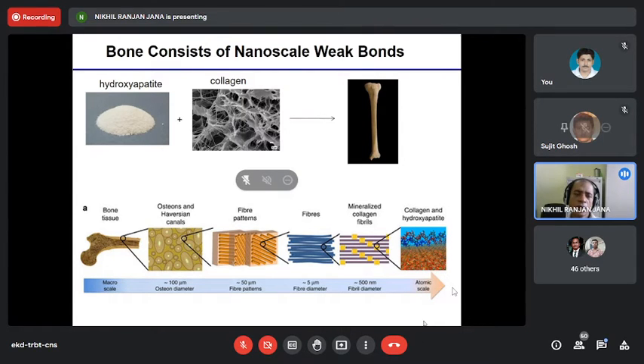Interaction between inorganic nanoparticles, hydroxyapatite nanoplatelets, with collagen fibrils, fibrillar organic materials, via multiple weak bonds. These bonds are called sacrificial bonds. Why sacrificial? Because under pressure, some of these bonds can break, sacrifice. By doing that, they can relax a little bit, but they don't break easily. And these are reversible bonds. Once you release the pressure, the broken bonds will connect again. So these are reversible but weak bonds, and many bonds. And this many number of bonds is possible because of nanoscale interaction between inorganic and organic components.